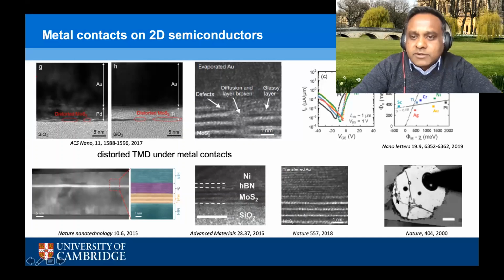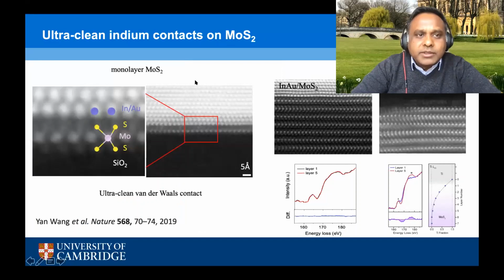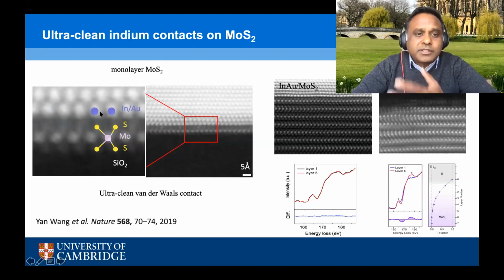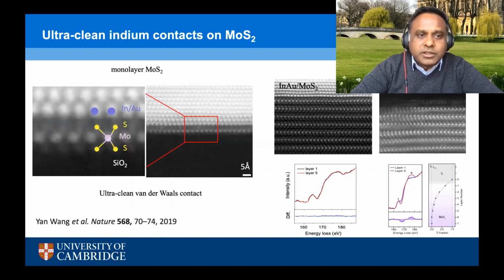So we took inspiration from this work by simply hypothesizing that if you have a very soft metal like indium, and if we deposit it very gently on top of a single layer MoS2 that's grown by CVD, we should be able to create a very clean interface. That is, we should be able to prevent any damage from the deposition of indium metal, because the evaporation is done at low temperature. The thermal energy of indium is also very low, so you can gently deposit onto the monolayer MoS2.